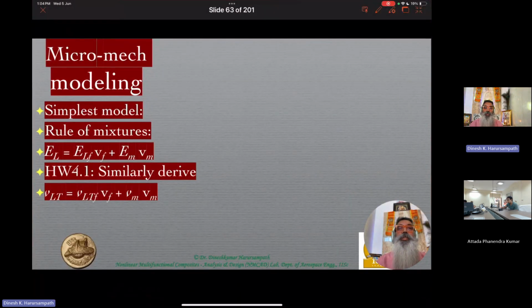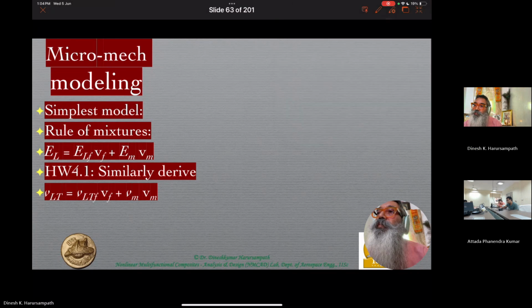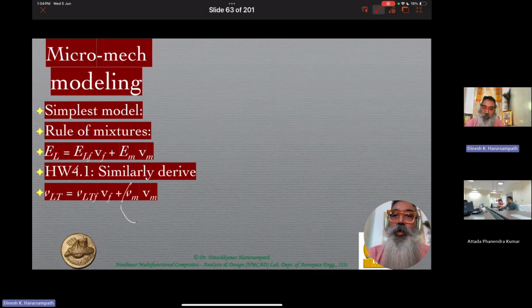What we're talking about is to prove that nu LT is equal to nu LT for the fiber times the volume fraction of the fiber VF plus the nu, which is the Poisson's ratio for the matrix, times VM. Strictly speaking, I should put LT there, but because it's an isotropic material, it doesn't matter. It's the same Poisson's ratio in any two perpendicular directions. Therefore, just write it as nu m, right? So I'm talking about this nu m over here, because it's an isotropic material.